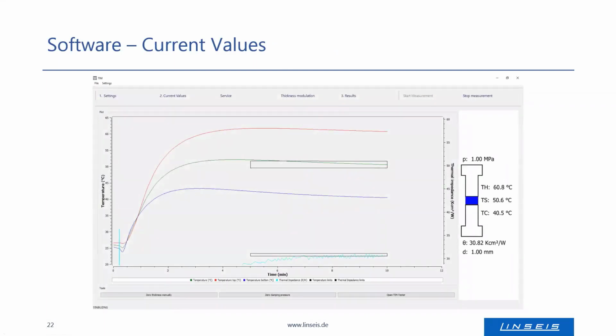In the current values window, one will see a graph which shows the temperature of the upper meter bar and the lower meter bar, and the average of them, which corresponds to the sample temperature. One can observe the change of the thermal impedance with time, and on the right, one can see the current values for the pressure, the thermal impedance, the measured or defined sample thickness, and again the temperatures.